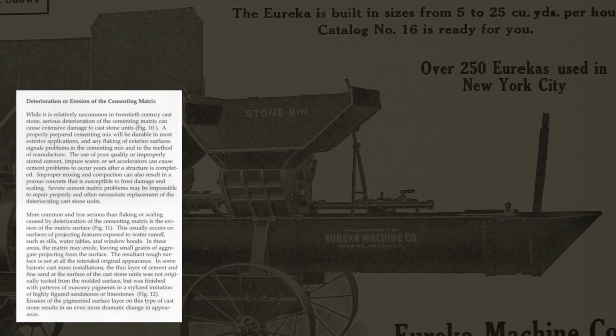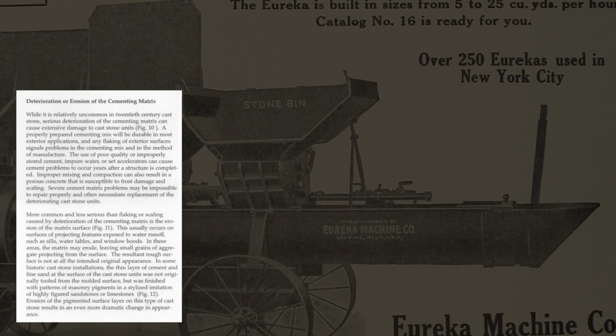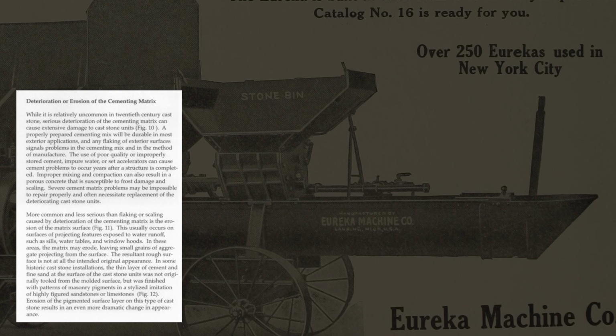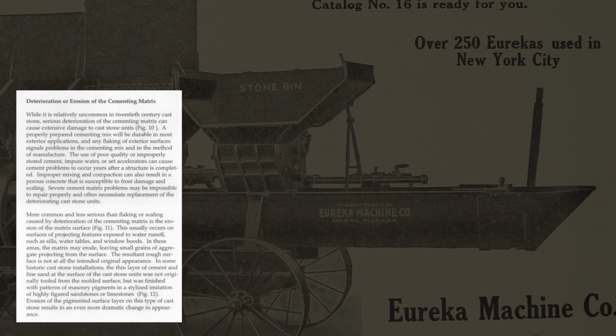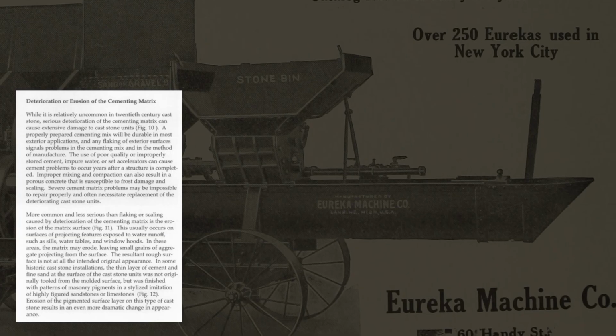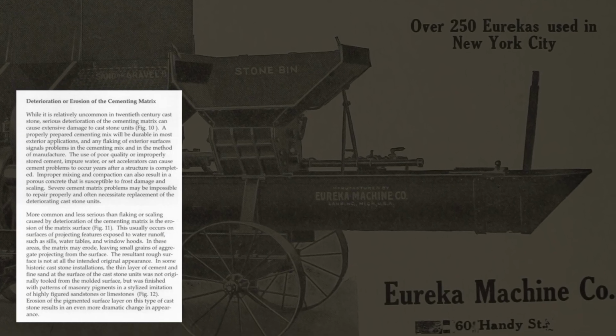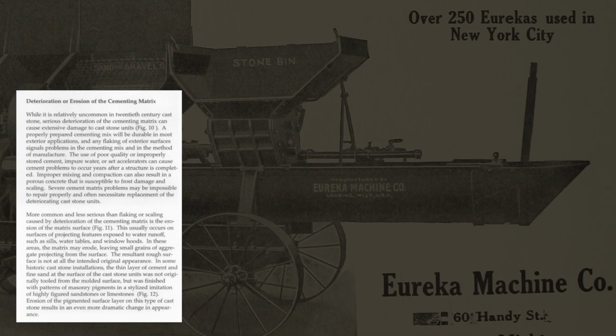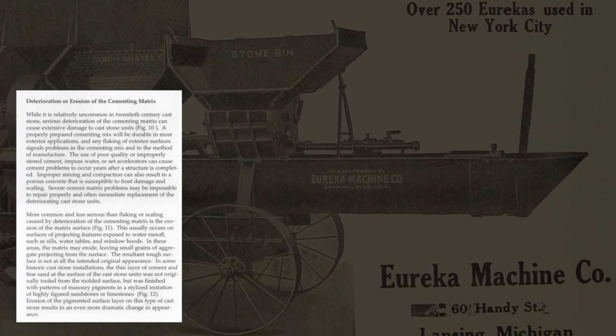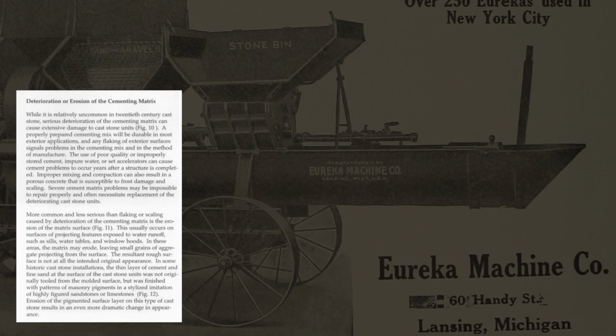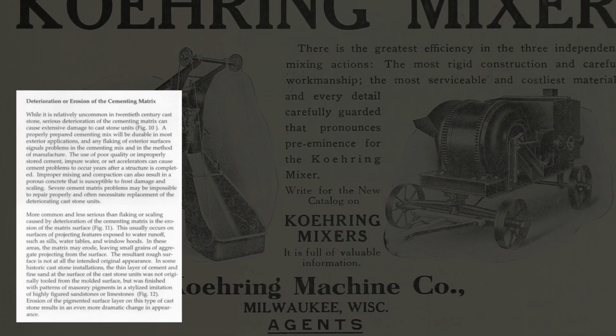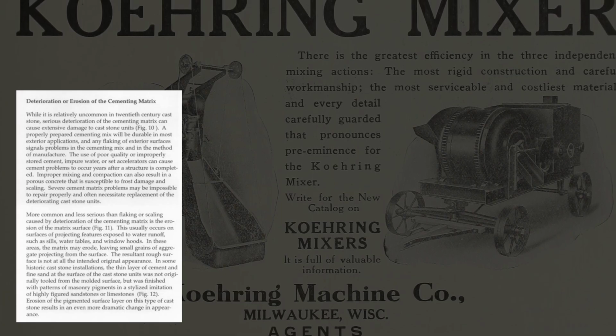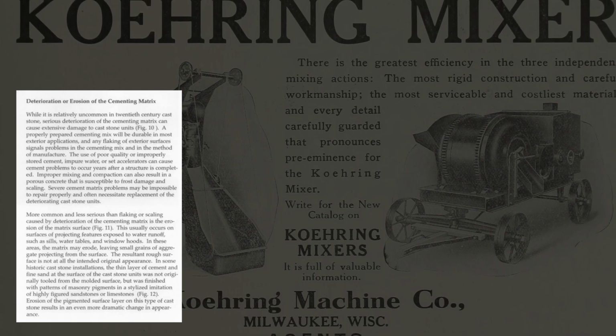Alright, let's read on. A properly prepared cementing mix will be durable in most exterior applications, and any flaking of exterior surfaces signals problems in the cementing mix and in the method of manufacture. The use of poor quality or improperly stored cement, impure water, or set accelerators can cause cement problems to occur years after a structure is completed. Improper mixing and compaction can also result in a porous concrete that is susceptible to frost damage and scaling. Severe cement matrix problems may be impossible to repair properly and often necessitate replacement of the deteriorating cast stone units.